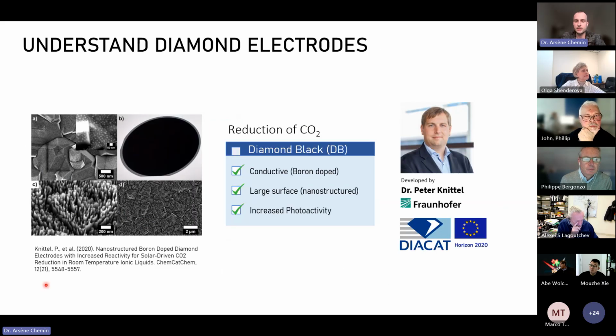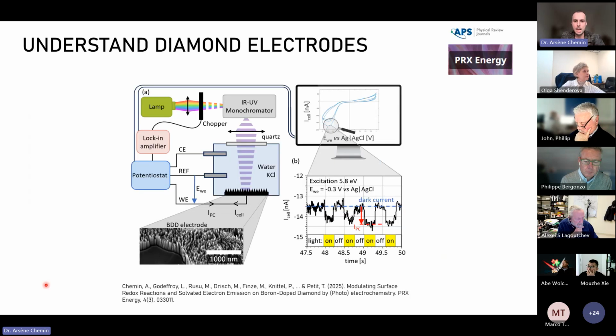So for instance, I can give you an example with the boron-doped diamond. Boron-doped diamond is a material which is great for electrochemistry. I studied quite extensively this kind of diamond black that was developed by Peter Knittel, which is a nanostructured, heavily boron-doped diamond. And to study it, we can perform some very simple electrochemical measurements.